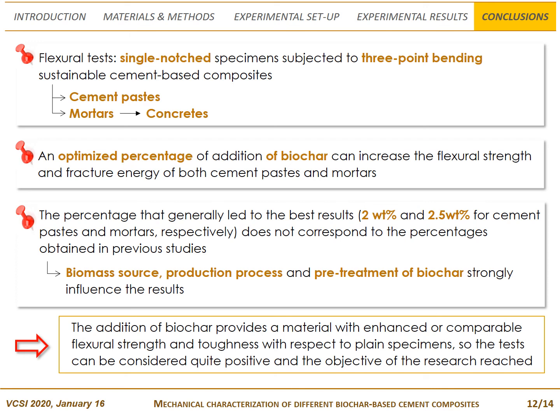Anyway, the results obtained show that the addition of biochar in the tested percentages provides a material with enhanced or comparable flexural strength and toughness with respect to plain specimens. So the test can be considered quite positive and satisfactory, and the objective of the research reached.